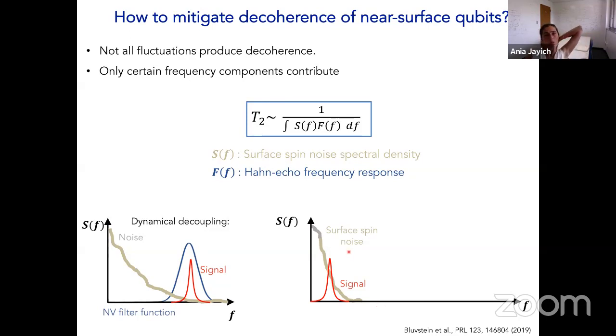And this relies on the important fact that not all fluctuations in the environment produce decoherence. We normally think of decoherence as interactions with the environment, entanglement with the environment, uncontrolled fluctuations in the environment, but not all fluctuations produce decoherence. Only certain frequency components in the environment contribute. So for instance, if you apply a Hahn echo sequence or some dynamical decoupling sequence, you're not sensitive to low frequency fluctuations in the environment. And if the environment is fluctuating at very high frequencies, those effectively get time averaged away, in analogy to motional averaging in NMR.